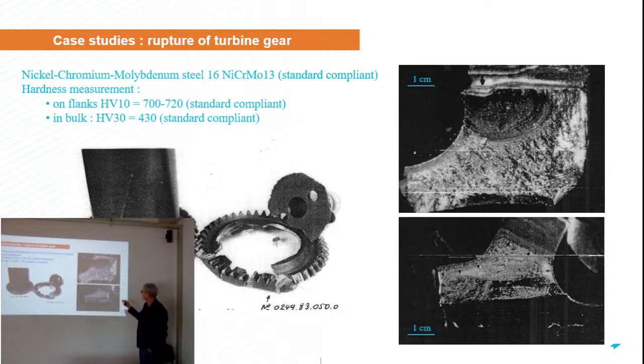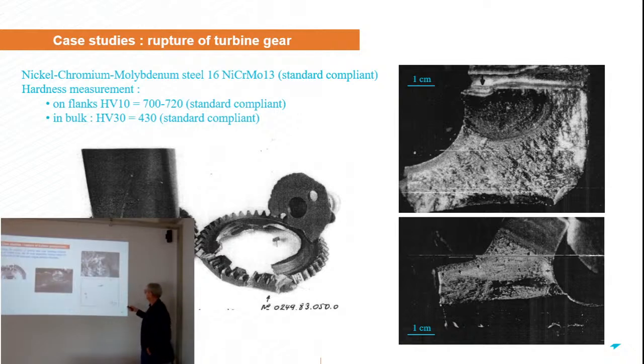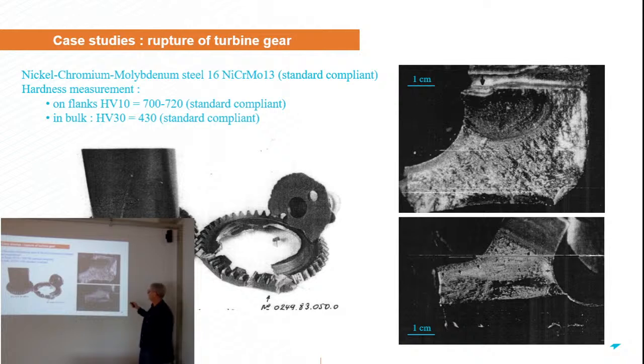And when you consider the concavity of the beach mark, you can go very easily to the initiation point, which is here, the zone where probably the stress intensity factor was the highest. So the initiation of the crack was somewhere here, and then the crack propagated this way until the remaining surface of material was not enough, sorry, to support the loading. Okay? So this is typical of